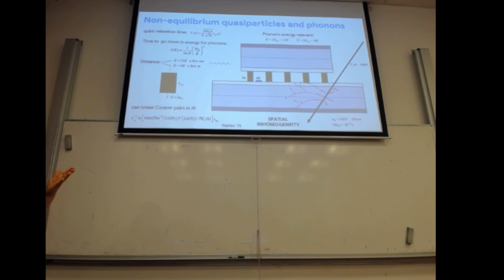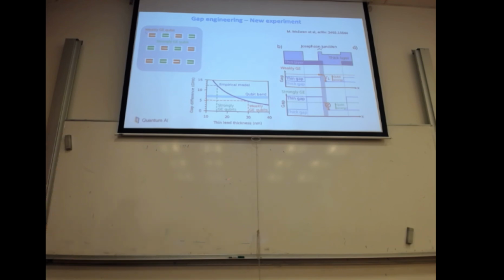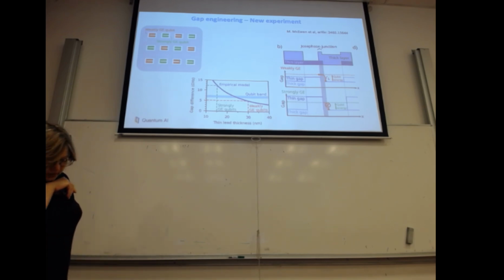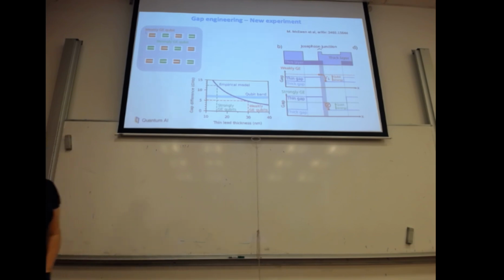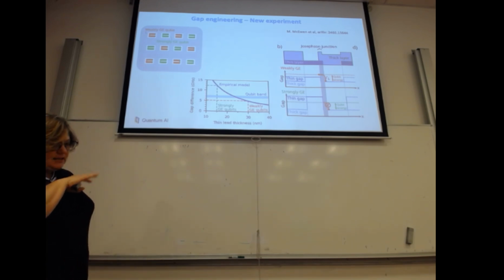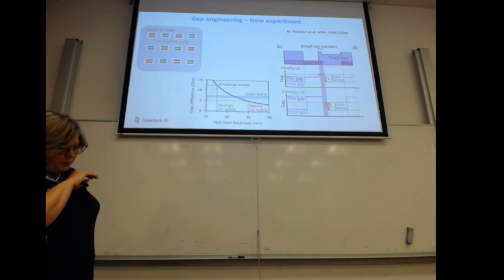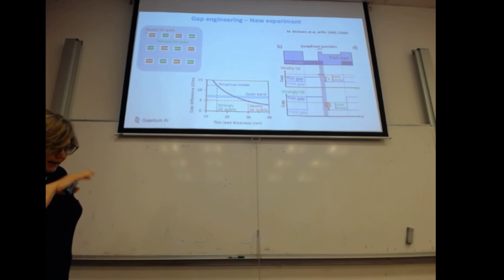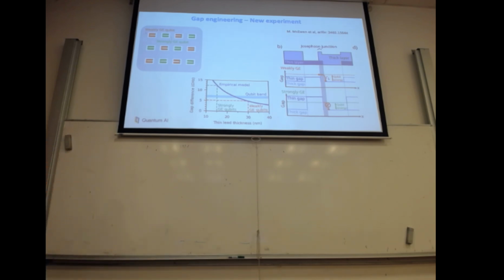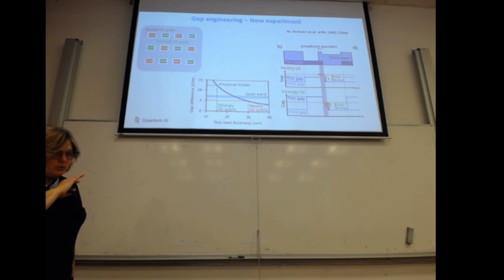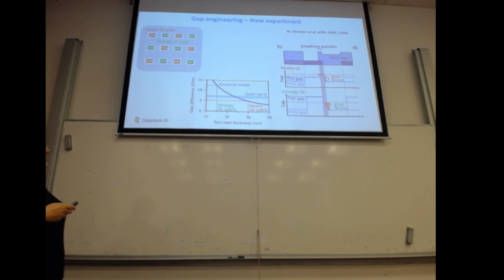So how can we correct this correlated error? The solution came by gap engineering. And this was a solution that was actually done, I think, more than 15 years ago by Gershenson initially also. There were studies beginning with SET, in which they were seeing that if you have gap engineering, you can control quasi-particle poisoning. Then Gershenson applied it to qubits. So we knew that if you want to control the poisoning of quasi-particles, there is a very good strategy, and that is to create some gap variation.